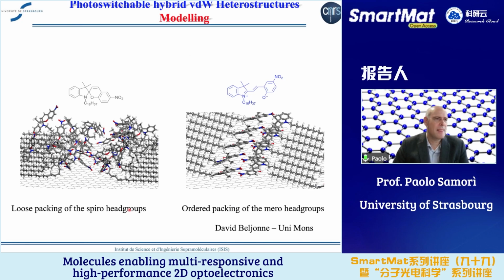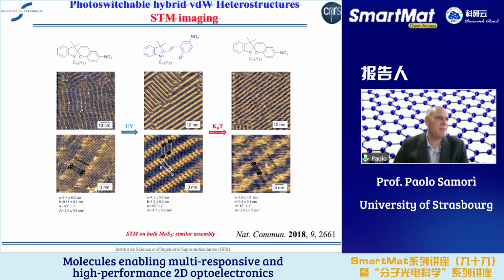Now, the occurrence of this isomerization is something that we can actually study also via modeling. Modeling, done in the group of David Beljonne in Mons, showed that the head group of the spiro, which is non-planar, doesn't pack firmly on the basal plane of the graphene, whereas the mero, which is more planar, packs very firmly. And actually this is reflected by the previous STM image by a higher resolution in the mero, where the molecules are better immobilized on the surface, and a more blurred image in the spiro, due to the fact that the head groups are not very well packed on the surface.